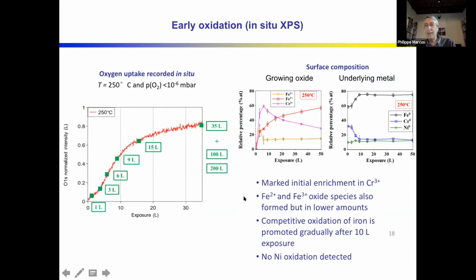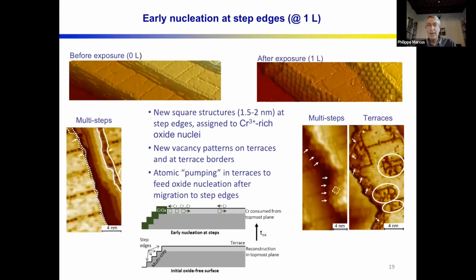Now we can look at that at the same time by scanning tunneling microscopy. And this is a high resolution image before oxidation with a very clean surface and these rows of vacancies. And when we expose this surface to oxygen, you can see these small islands here, which are nuclei of oxides. And you see that they form at the step edges. They don't form at the surface.